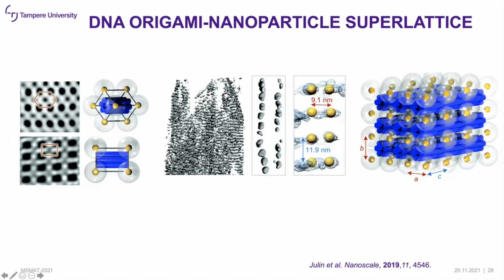Here is electron tomography, from which we can extract the location of the nanoparticles, and then we can create a model to suggest the actual packing of the structures. So what we do is that we create structures, we study them, and then we do microscopy, small angle X-ray scattering, and circular dichroism, and then eventually do the reverse engineering to propose the structure based on the experimental evidence.